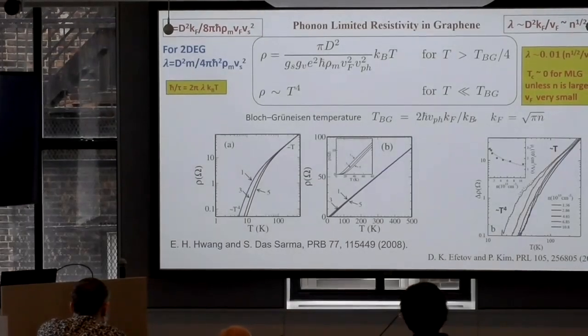10^14. And then Philip saw our paper and called me, and I said, we cannot go all the way there, but maybe we can see this T^4 behavior, which nobody has ever seen clearly. You cannot really see the Bloch-Gruneisen T^4 behavior in regular metals. It's very difficult to see. Since our density is very high, this temperature is pretty high, of the order of 50 Kelvin, 100 Kelvin. So you can clearly see it going from linear in T to T to the power 4. So they, very smart experimentalists, snatched victory from the jaws of defeat. They did not see superconductivity.